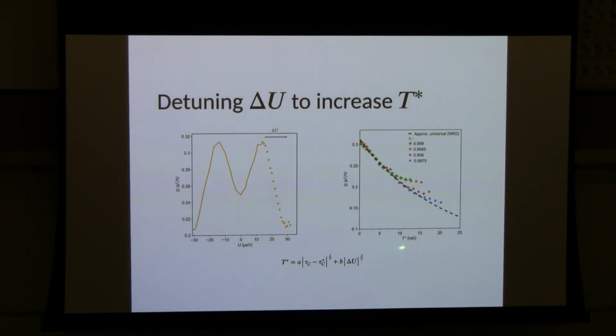And if we use that, we can plot this scale T star, this effective energy scale, and plot conductance. And for a bunch of different data, we can plot them all in the same plot, and you see that to a reasonable extent, they fall together on a calculated line. And then you can also see that they deviate from it.